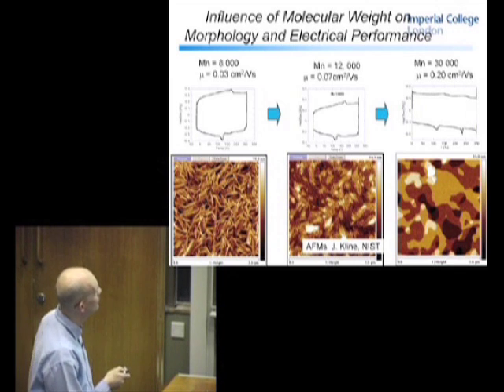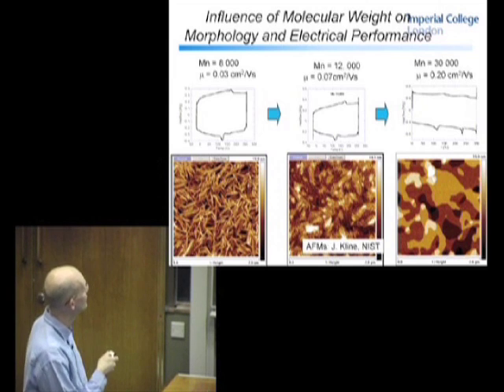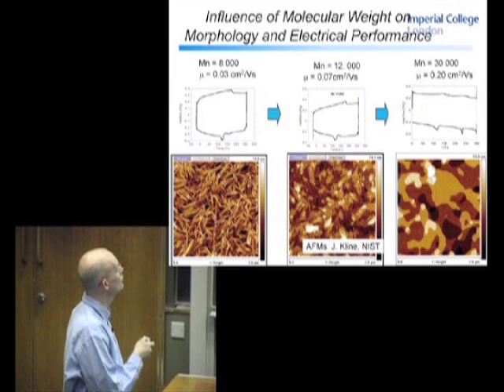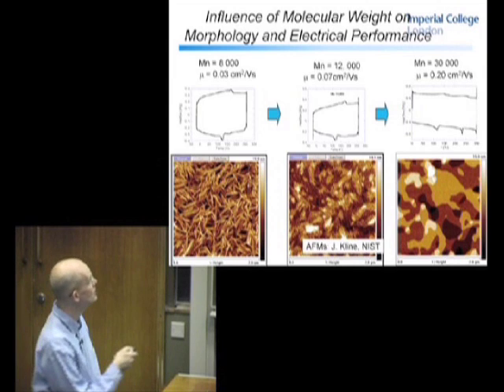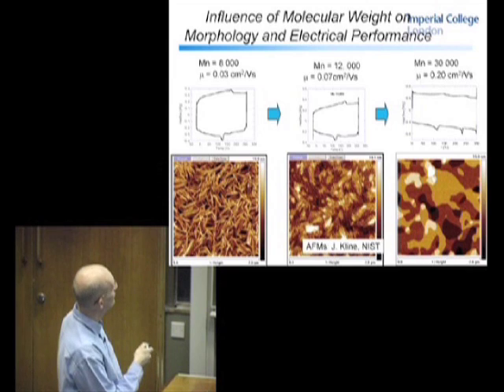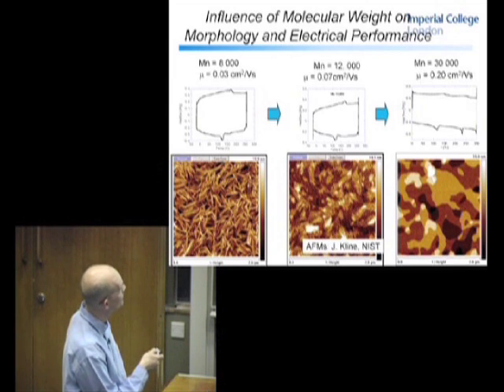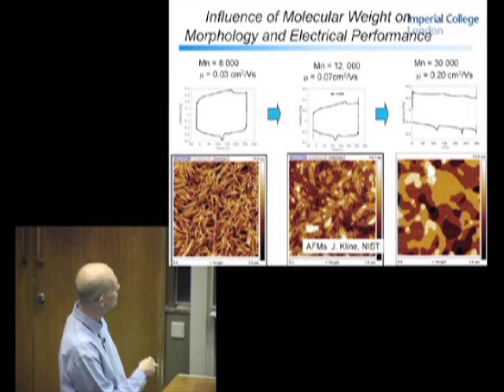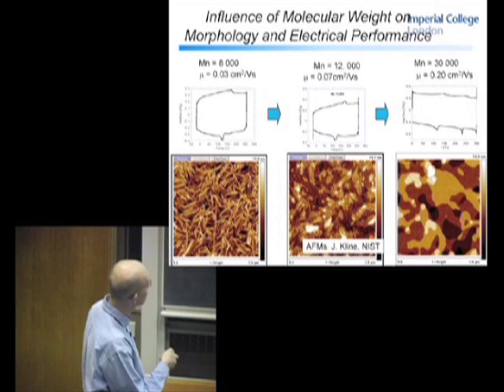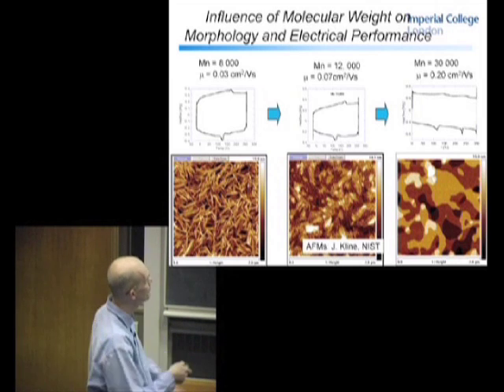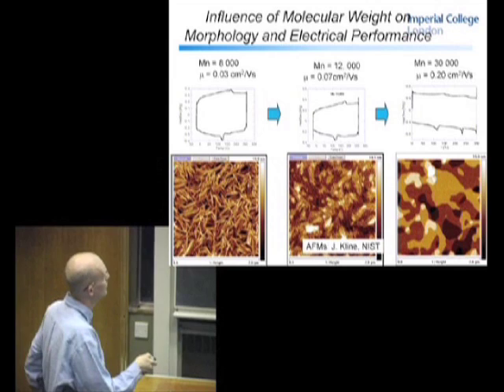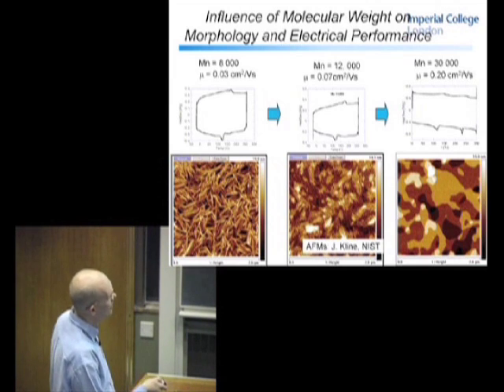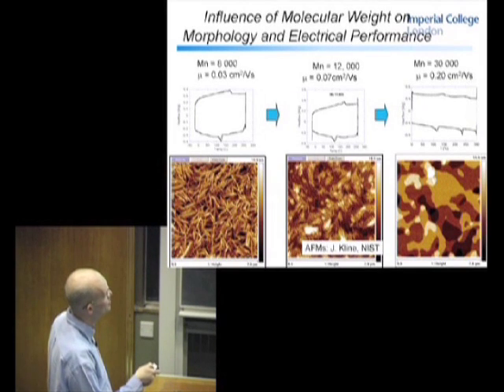A lesson for polymer chemists is that if you make a polymer material with a number average molecular weight of 8,000 and the performance is not so good, don't give up. It could be that in fact you just need to improve your polymerization process and move to a higher molecular weight. You see here that this again is a thermal characteristic, same polymer, PBTTT, low mobility, one thermal transition, quite low temperature transition. As you start to increase number average molecular weight, performance jumps a little. You start to see almost evidence of two transitions here. You've moved from this one-dimensional whisker-like morphology, where you've got these almost like wires where the width of the wire equals the length of the chain, so you don't have two-dimensional or three-dimensional order. This is a sort of hybrid structure, moving again to these very highly ordered systems. You have two transitions and much higher performance.